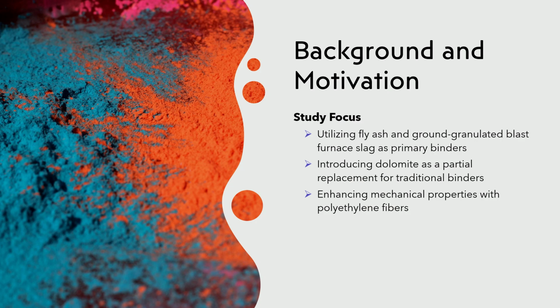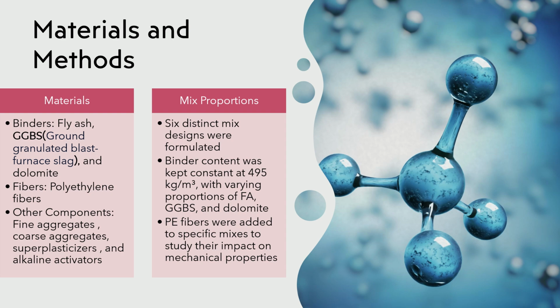So the focus of our study was utilizing fly ash and ground granulated blast furnace slag as a primary binder, also introducing dolomite as a partial replacement for traditional binder, and enhancing mechanical properties with polyethylene fiber. So we used different materials. As a binder, we used fly ash, GGBS, and dolomite. And we used polyethylene fiber, and other components were fine aggregate, coarse aggregate, super plasticizers, and alkaline activators. We used different mix proportions. All the binder content was 495 kilogram per meter cube, and PE fibers were added to specific mixes to study their impact on mechanical properties.